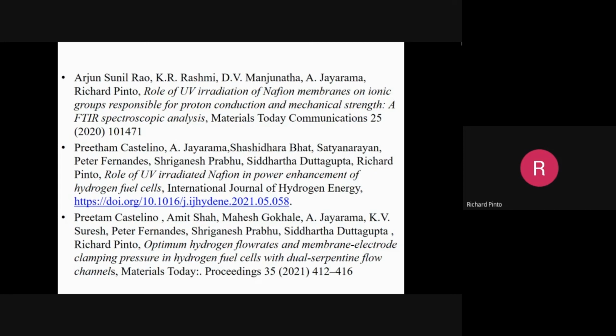This is the work done on the initial design of the hydrogen fuel cell, and the design of the UV exposed hydrogen fuel cell giving a much higher power density, a factor of 2 higher. And this is for the design of optimum membrane electrode assembly clamping pressure in a hydrogen fuel cell with dual-serpentine flow channels. Here, of course, he contributed in the design of a humidification setup, which is critical for operation and long life. So these are all publications.